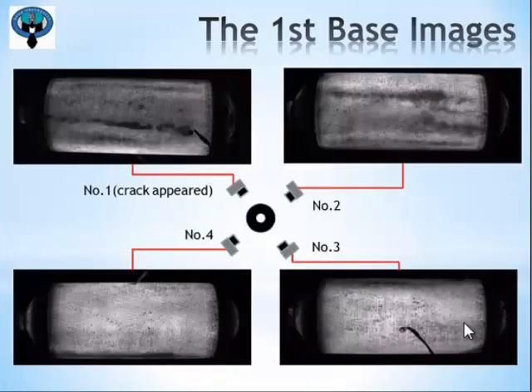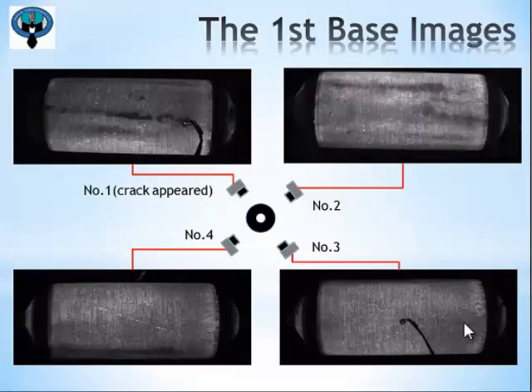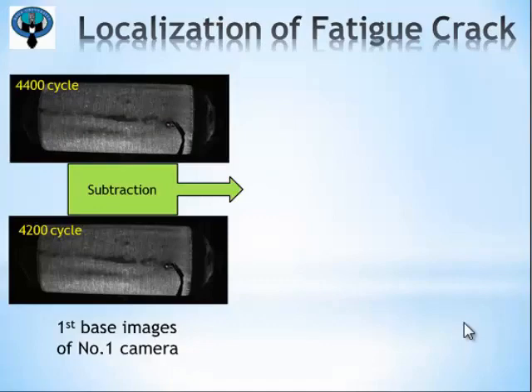Okay. These movies show the first base images of every high-sensitivity mode of 4 side view cameras. You can find patterns of carbon fibers in these images. In the movies of number 1 camera, a slight indication pattern of fatigue crack appeared at the last image. By simple subtraction among past base images, fluctuation of ML pattern is extracted.